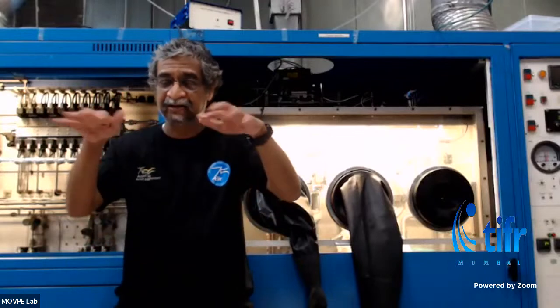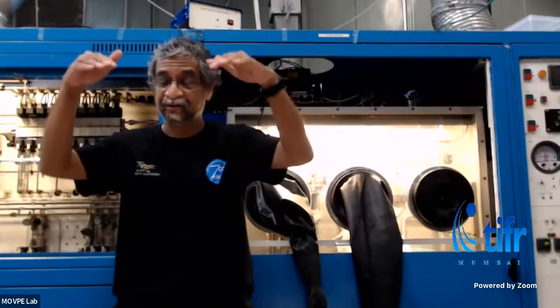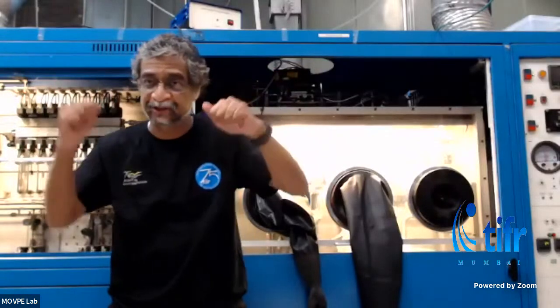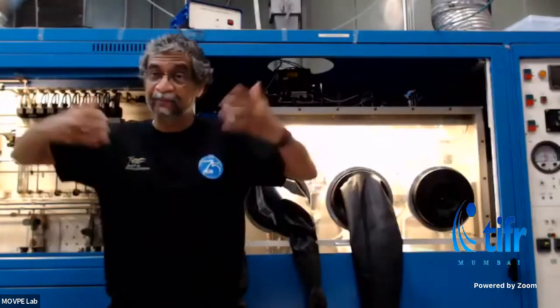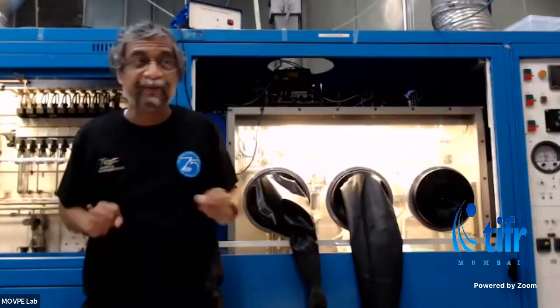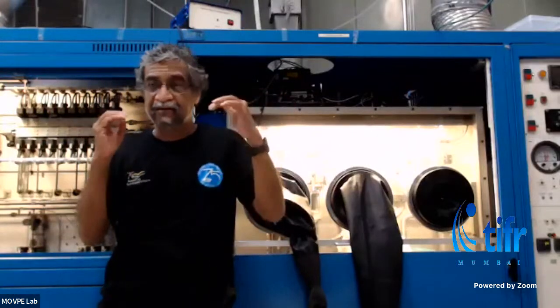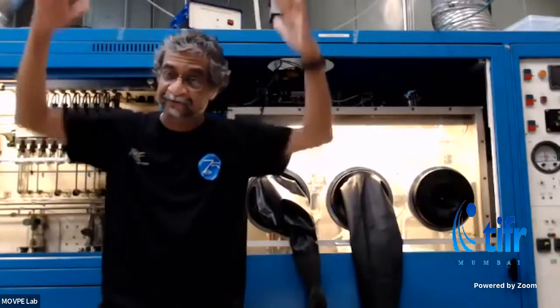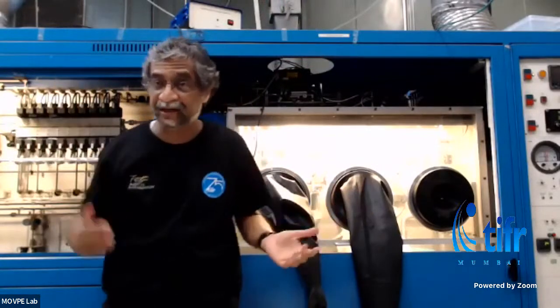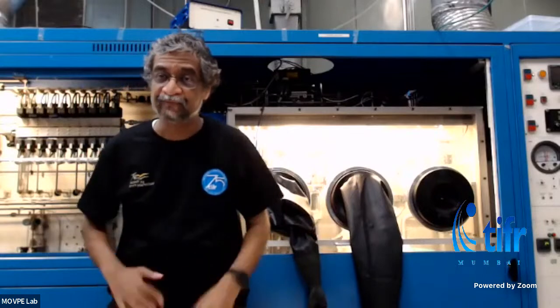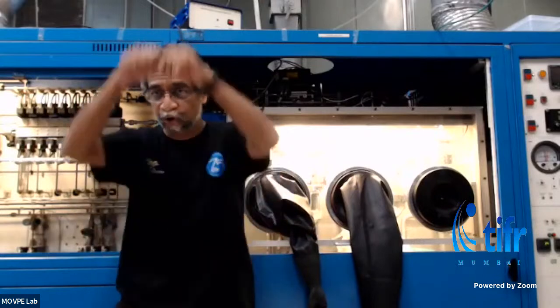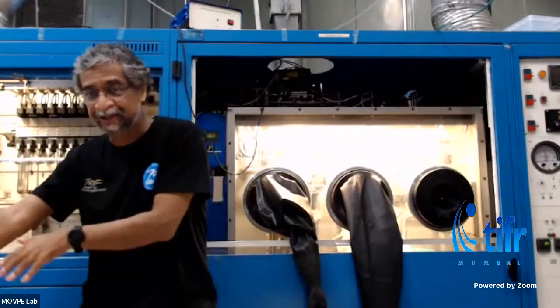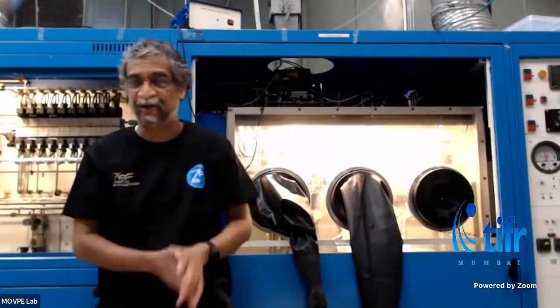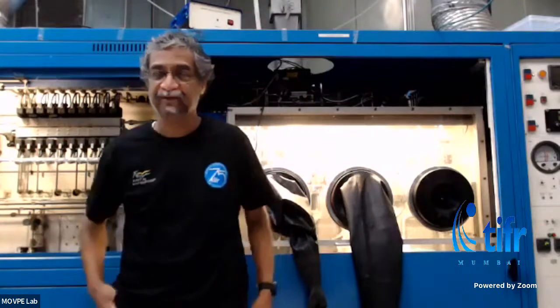If you want to grow gallium nitride, it's higher. It starts at 850, 900, 1000, 1040. That's the normal temperature. If you're growing aluminum nitride, that likes to be hot. Aluminum nitride grows at 1080, 1100, 1150 degrees centigrade. There are newer reactors which can go up to 1400 degrees centigrade. So it depends on the material. Generally, when you go down the periodic table, temperature goes down. You go up in the periodic table, temperature goes up.